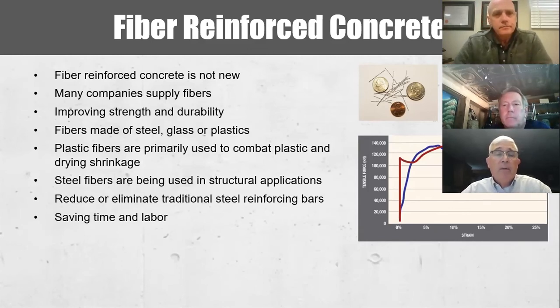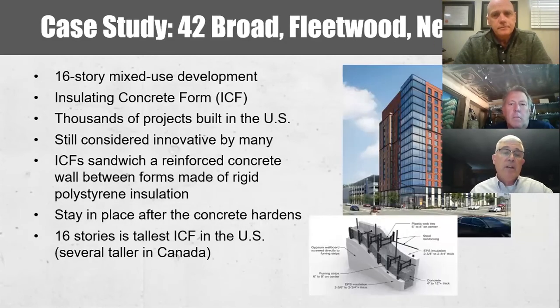The plastic fibers are primarily used to combat plastic and drying shrinkage cracking. The steel fibers can be used in structural applications to effectively reduce or eliminate the traditional steel reinforcing bars, which in turn helps to save time and labor on job sites. Here's a case study where helical steel fibers were used to reduce the amount of traditional horizontal steel in this project.